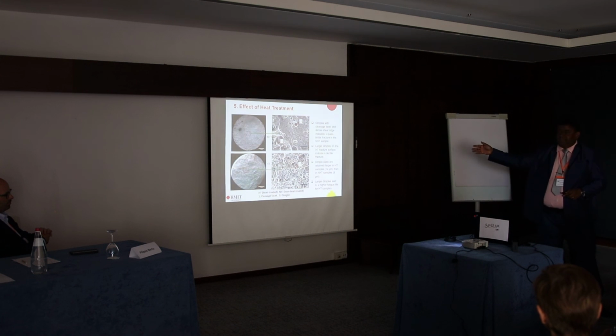Okay, with that, I'd like to conclude my presentation. But remember, the whole key thing is that we did some tests, looked at the results, made conclusions, then went down to the fundamental physics, metallography or microstructure effect to understand that. For example, with heat treatment, you can see that if you have no heat treatment, you get these dimples with cleavage faces, which will cause a brittle fracture and lower fatigue life. If you have heat treatment, you have larger, round dimples, which will cause a ductile fracture. That again explains why you see a different effect.